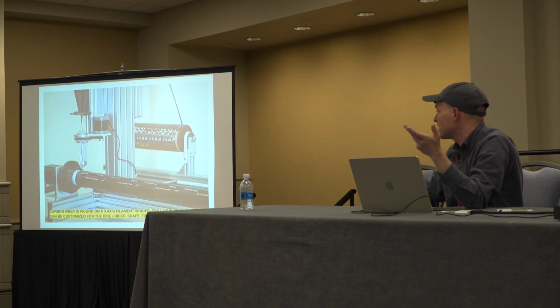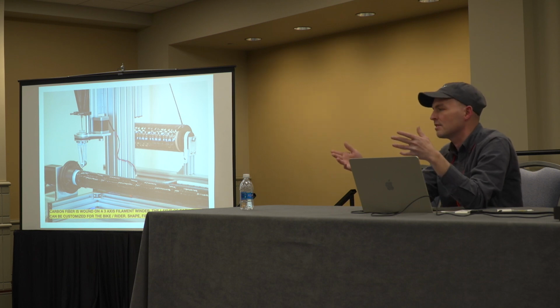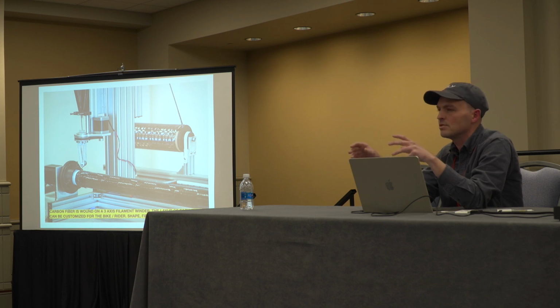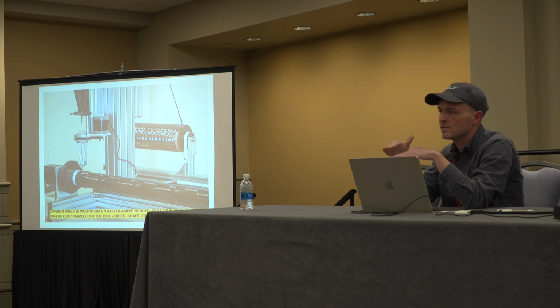This is the winding process. I talked about this a little bit before, but I can customize pretty much everything about the tubes, to a degree. So tube diameter, tube shape, and then the layup itself. So how many layers of carbon there are on the tube, which would determine the thickness, but also the orientation of those fibers, which will determine the characteristics of the tube.